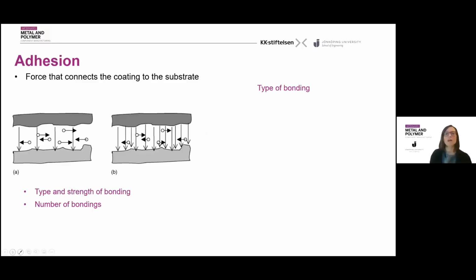So adhesion has been coming back both for mechanical durability as well as corrosion durability. Let's look a bit at what adhesion is. Adhesion is given by those forces that connect the new material on the surface to the material in the substrate. It's a sum of different bondings that form between 2 different materials. Therefore, this force depends on the type of bonding and their strength, as well as the number of bondings, because we are adding and joining materials that could be very different - we can add metal on metal, but we can also add polymer on metal.